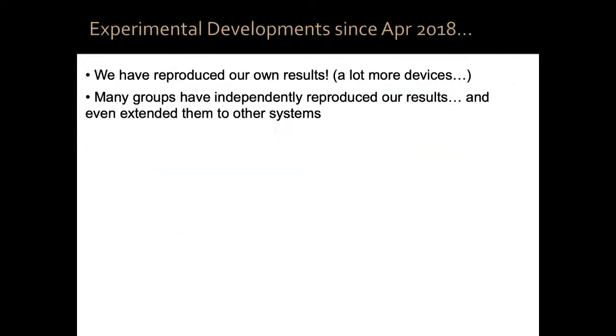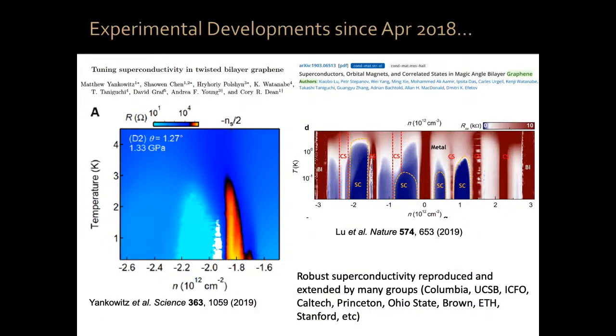The second thing that happened, which is much better than reproducing your own results, is when other people reproduce your results. Only then does it become real science. So many groups have independently reproduced our results and extended them in very interesting directions. The first two papers to reproduce our results: the first was a collaboration between Cory Dean at Columbia University and Andrea Young at UCSB. Not only did they reproduce our results, they also extended them in a very interesting experiment under pressure, and they were able to tune the superconductivity in this system.